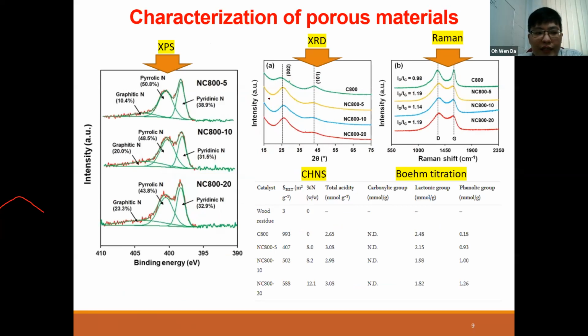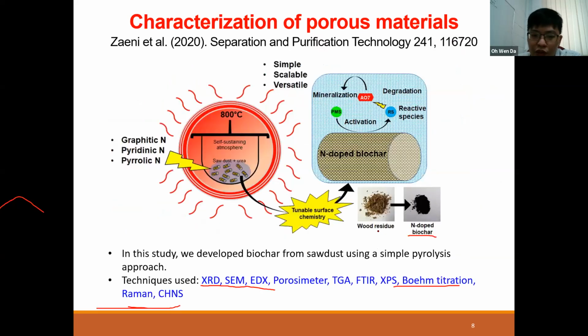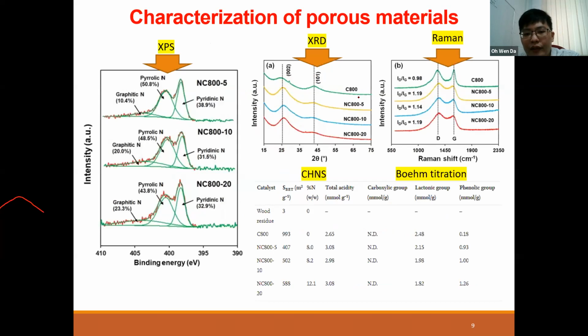First one is that in terms of XRD, we use this technique, and we look into the carbon phase that we have. Before that, for this conversion of wood residue or sawdust, we use sawdust as our biomass precursor, or bio waste, and we add in different amounts of urea. So we mix the sawdust with urea, because urea is a good nitrogen source. We mix it, and then we carry out pyrolysis to get the materials that we want. And we vary the amount of urea from 5 gram, 10 gram, and 20 gram.